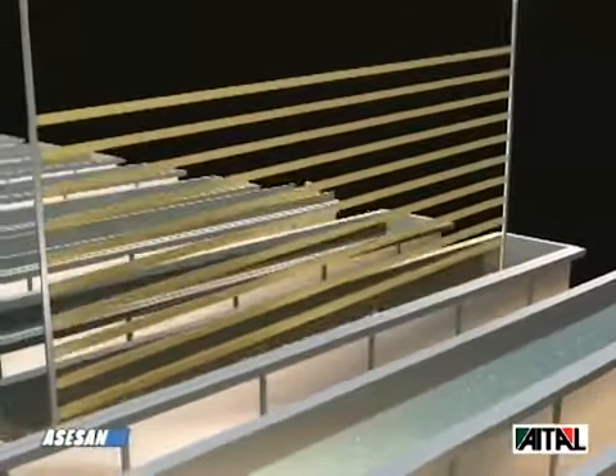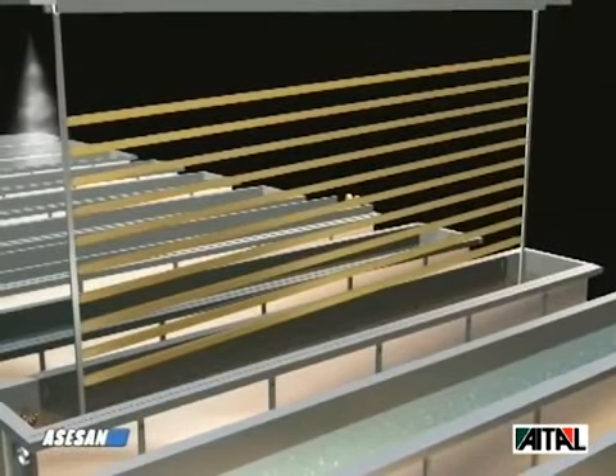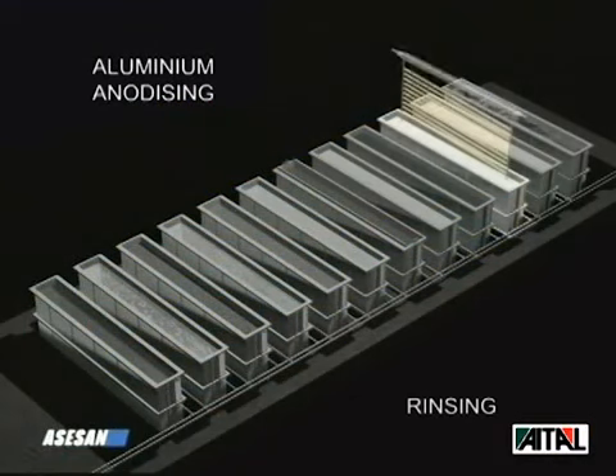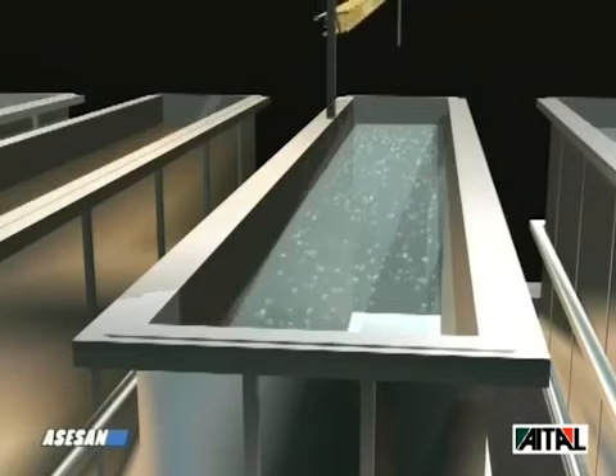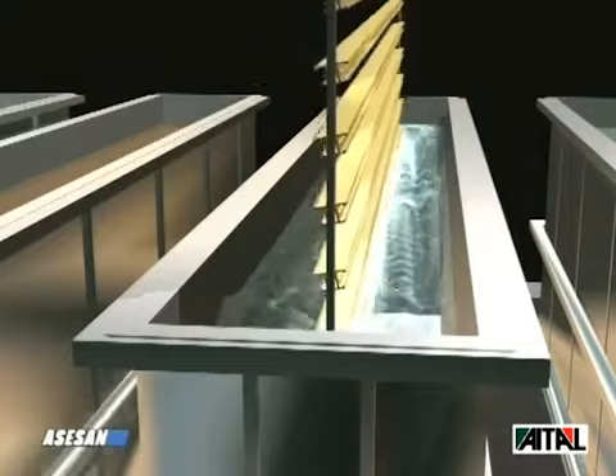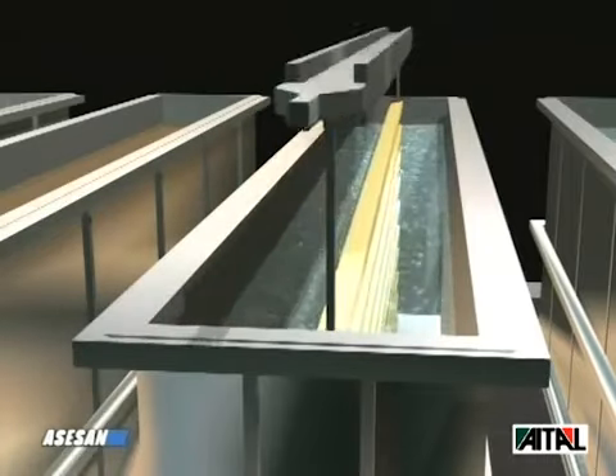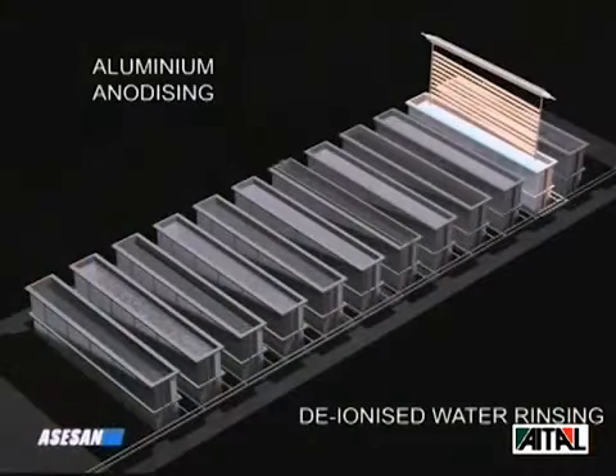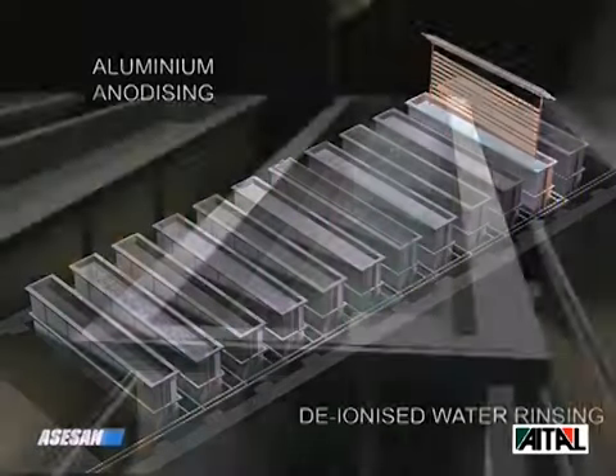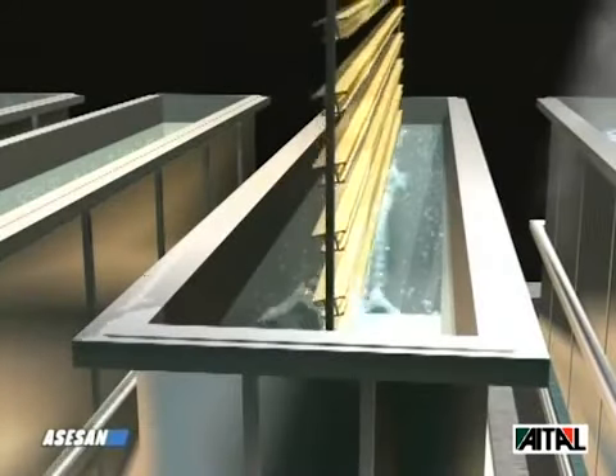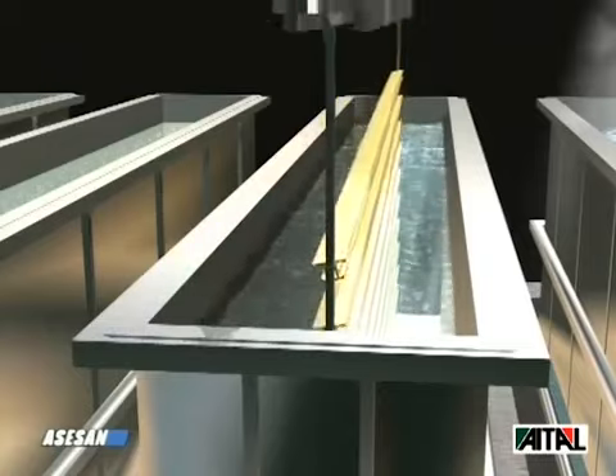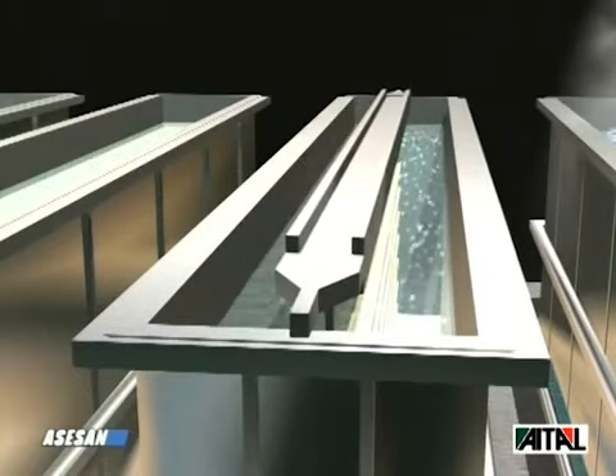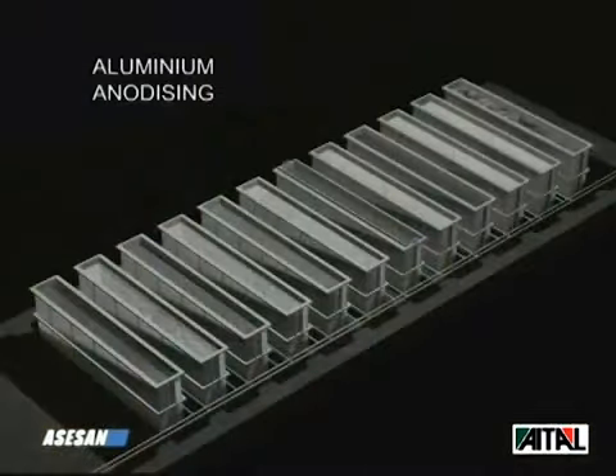When the anodic layer is formed and the coloring process is complete, the pores must be sealed with a sealing treatment. First of all, a careful rinsing with water is essential. A second deionized water rinsing follows to completely remove any acidic residue from the pores. Finally, the porous structure must be sealed.